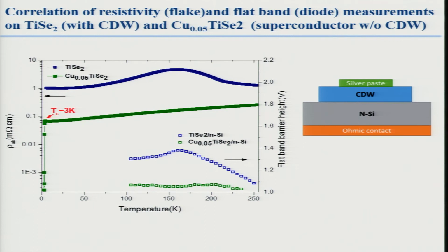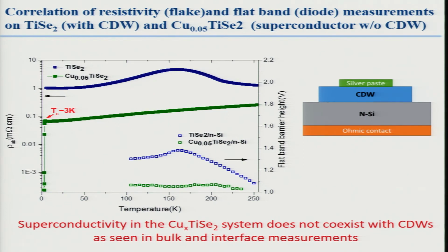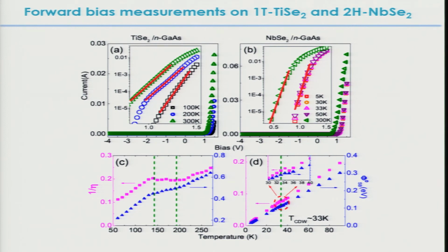And this is opposite to the case where we've induced a gap in the tantalum disulfide. So superconductivity does not coexist with CDWs when it's doped with copper. We've gone back to the pure titanium diselenide and the niobium diselenide, done our current voltage characteristics, and seen little features here, which again, just like in the tantalum disulfide, mimic what we see in the resistance transitions.